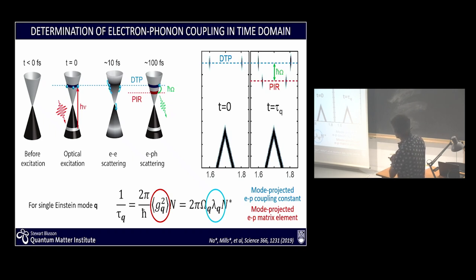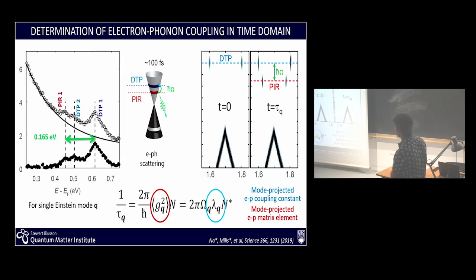And so this is the beauty of this simple relation. If you have the resolution to see these features, you can extract directly the tau q, the electron-phonon scattering time, and immediately you can get either the electron-phonon matrix element for a given q or the electron-phonon coupling, as you wish.